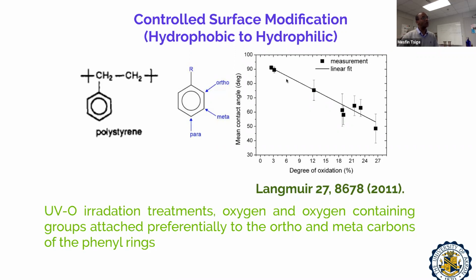Depending on how long they expose the surface to this UVO radiation, they can actually control the degree of oxidation, hence the hydrophilicity of the surface. So this is in a much controlled way. The way to think of this is without changing the roughness of the surface, because roughness has its own consequences on the contact angle, just only changing the chemistry and allowing the effect that we see is based on functional groups.